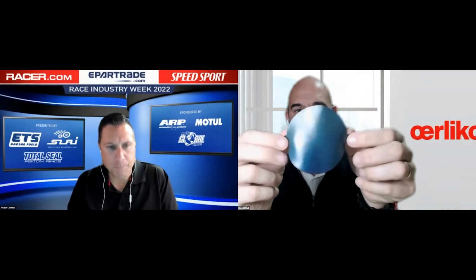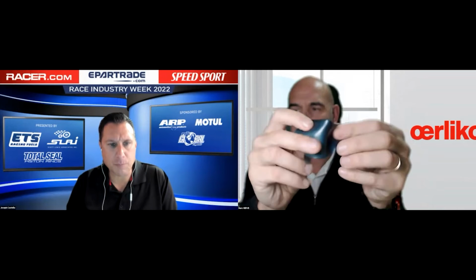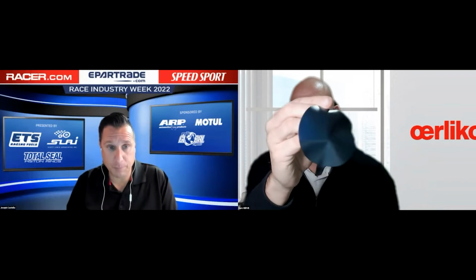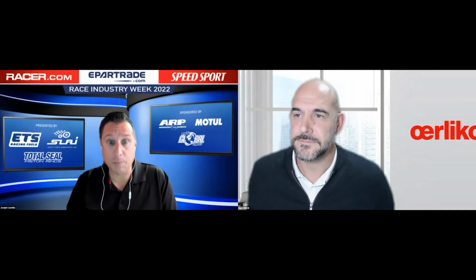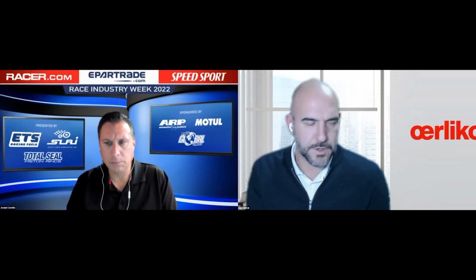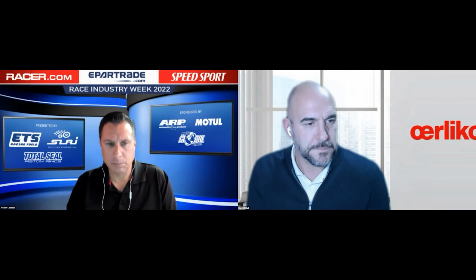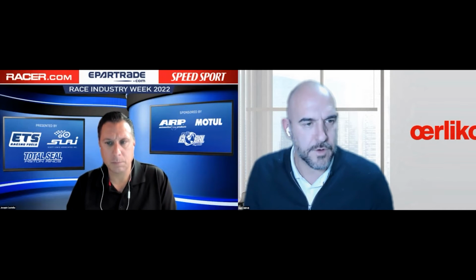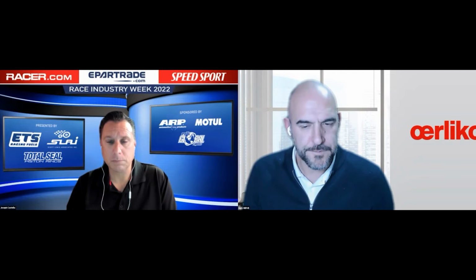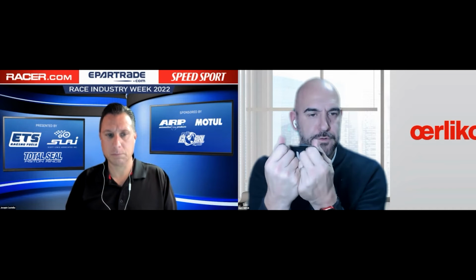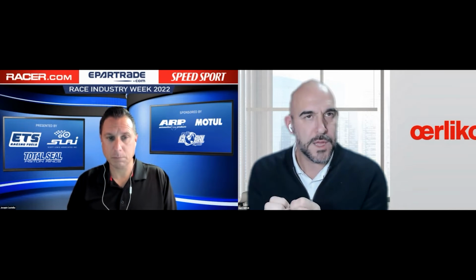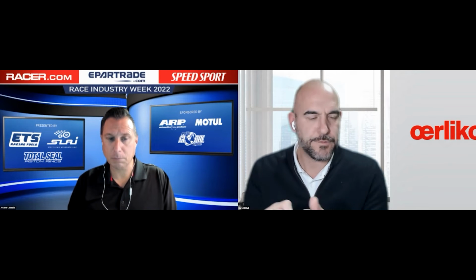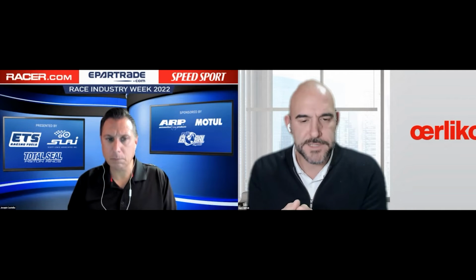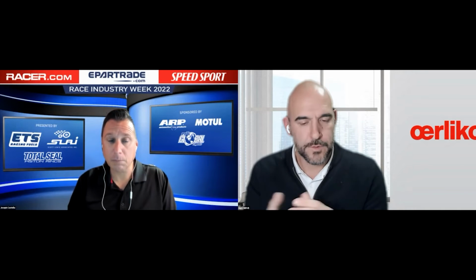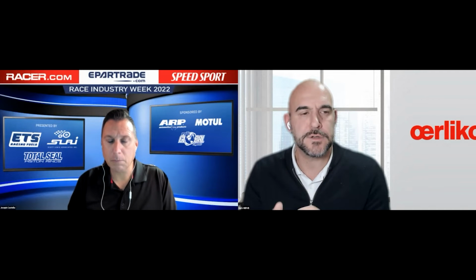There you go. So you can see that membrane. So very thin membrane. As you can see, the color is slightly different. So it has been coated. And as you can see, I can definitely twist it all the way around and put it back into one piece. So here, again, it's really linked to the fact that the coating is really thin, but the adhesion is really good. The thing is, if you look at the parts under a microscope, you will see that actually the coating is fully cracked. But this is the beauty of the solution: if you stretch the parts, you can see that all these small islands between the different cracks will actually follow the elastomer. And when you release, basically, it will all come back together. So the coating will crack, but it doesn't mean that we're going to lose the adhesion of the coating on the part itself.